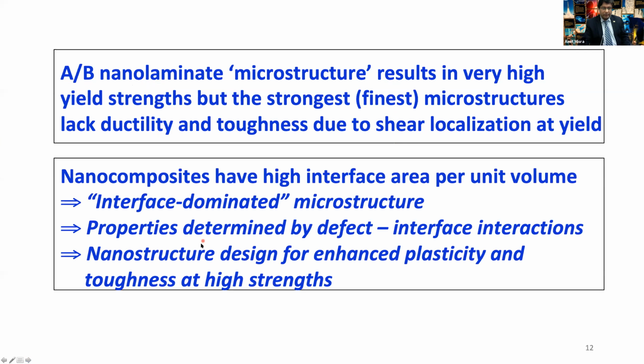We also recognize that these kinds of nanocomposites have high interface area per unit volume. So we have to start to think of this microstructure in a different way. Instead of a size like a grain size or layer thickness, we have to think of it as microstructure that is interface dominated, because it's mostly interfaces, and the properties are going to be determined by this defect interface interaction, which means that there needs to be a way to design these interfaces to enhance plasticity and toughness while maintaining high strength, which is a new direction of research in this field.